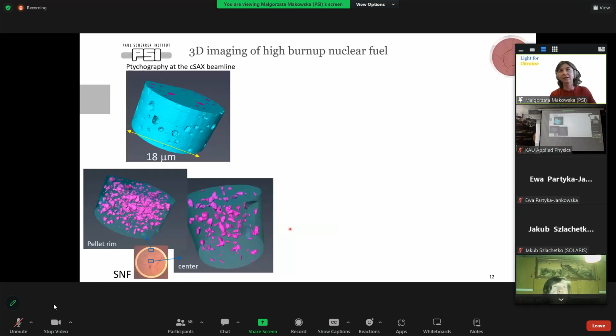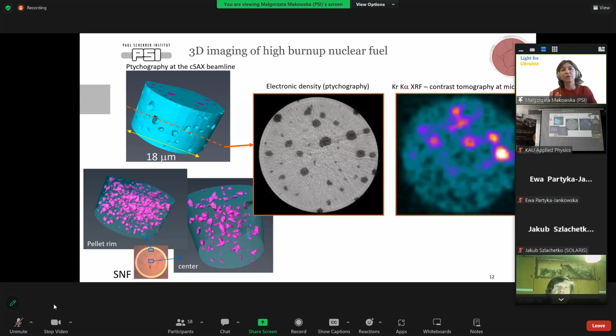And here is an example, again, from spent nuclear fuel. What you see here is a high resolution imaging based on attenuation. Actually, this one is on phase contrast, but we also have it based on attenuation. This is a result of ptychography performed at the CSAXS beamline. And you see that these are two pillars extracted from different parts of the spent nuclear fuel. And in this signal, with very high resolution, we could see that we have some inclusions inside, or pores, or whatever they are. However, from this contrast, we couldn't say what they are. We couldn't even say if they were really pores or filled with something.